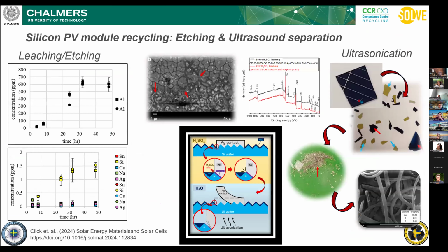But after a while, we understood that with etching of the surface, which is the silicon nitride layer for silicon PV modules, we can remove the first touching layer. By removing or disrupting this layer, we can release the silver contact with ultrasonic treatment. By releasing the silver contact, with a simple method we can purify the silicon wafer, and by removing the silver contact, we can obtain high-purity silver.